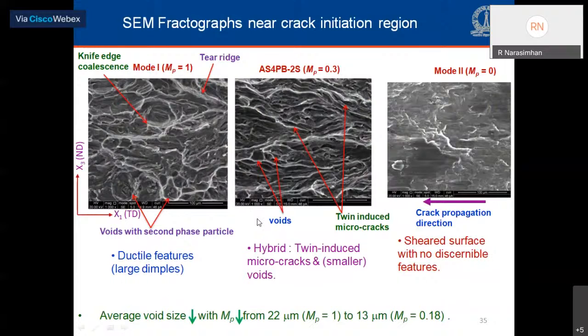Taking a look at the fractographs, we again notice transitions in the fracture mechanism. The left side fractograph is for the mode 1 case, and here is essentially dimple fracture with a lot of inclusions sitting inside the dimples. In the mixed mode case in the middle, we see a hybrid mechanism involving twin-induced microcracks, which are those elongated grooves or slits, as well as some small voids. And in the mode 2 case, we see a heavily sheared fracture surface, and this is possibly because of closure of the crack and rubbing of the crack faces taking place.